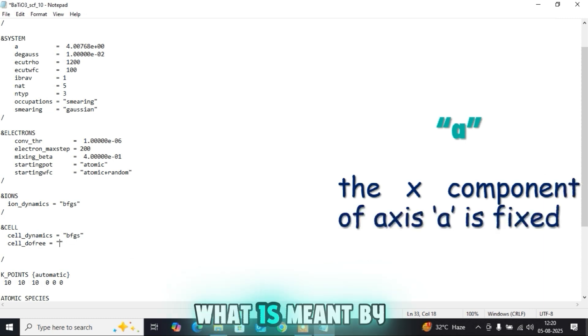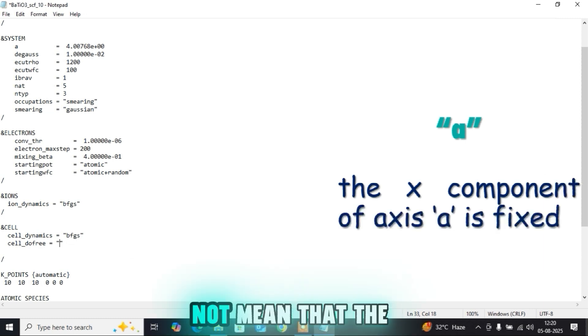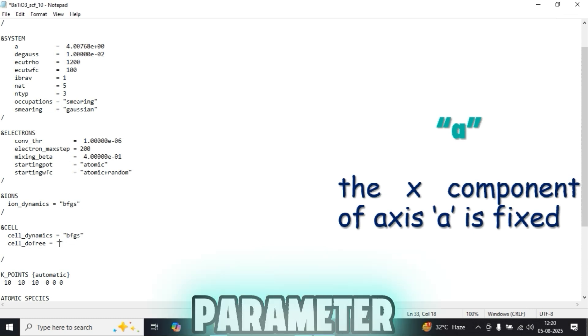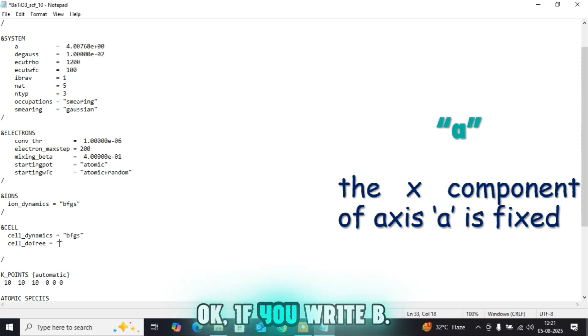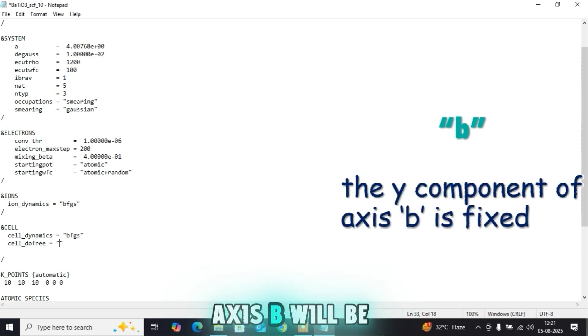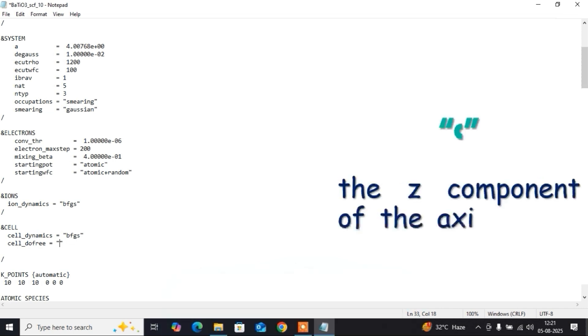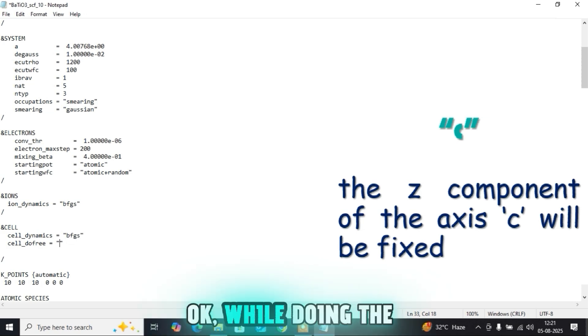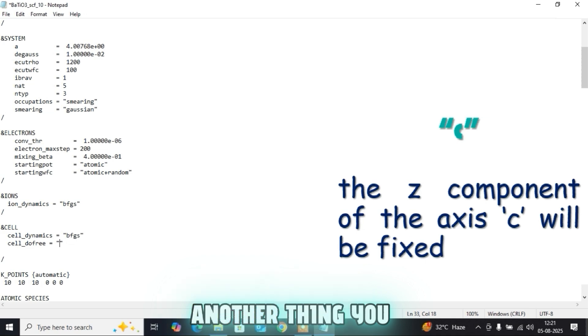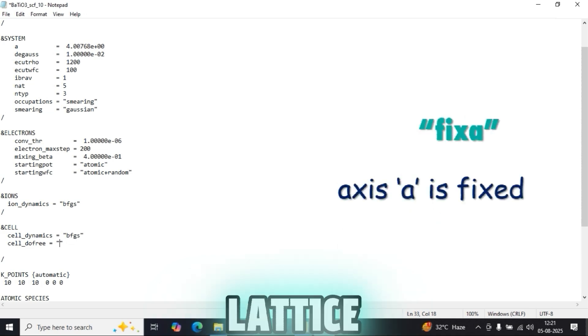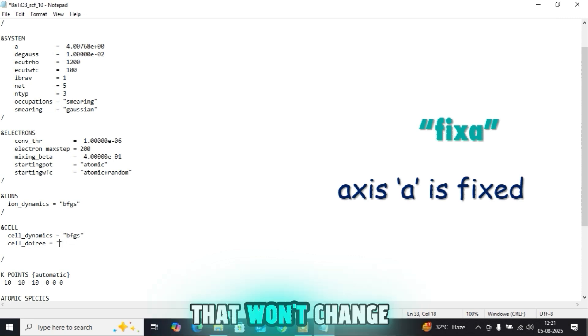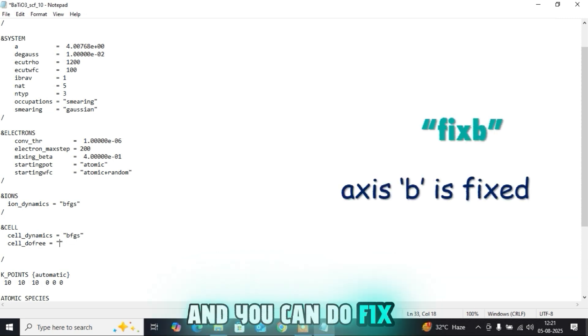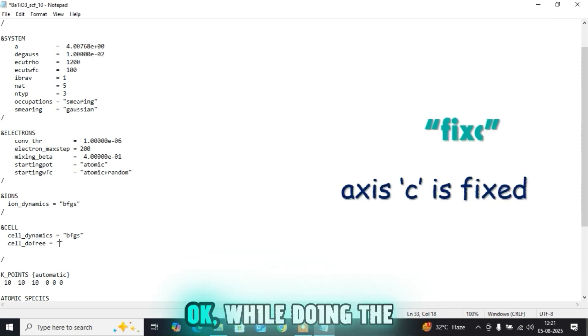Another option is 'a', which does not mean the lattice parameter a will be constant — it means the x-component of lattice parameter a will be constant. If you write 'b', the y-component of axis b will be constant. If you write 'c', the z-component of axis c will be constant — it won't change during the relaxation. Similarly, you can do 'fixb' to fix lattice parameter b and 'fixc' to fix lattice parameter c during the vc-relax calculation.